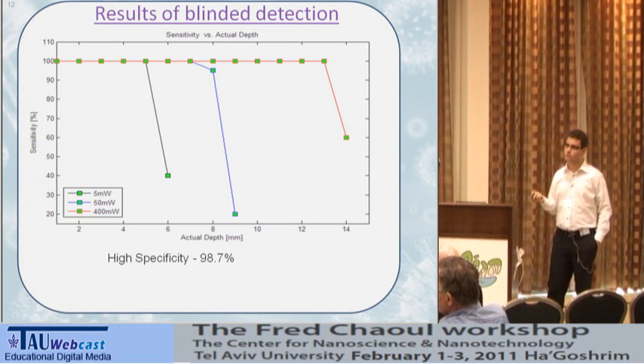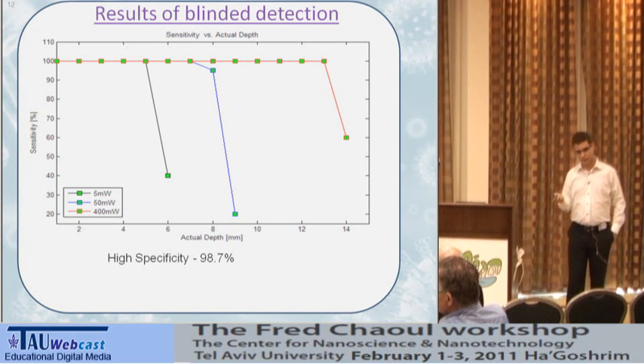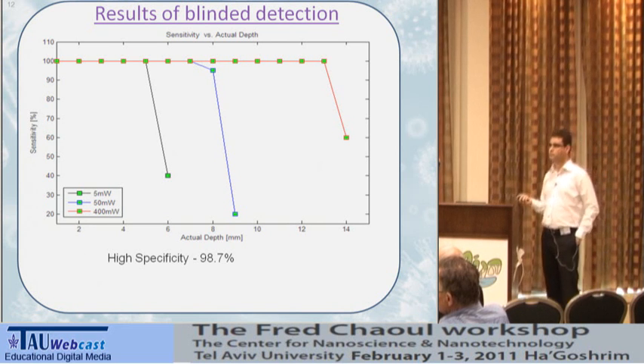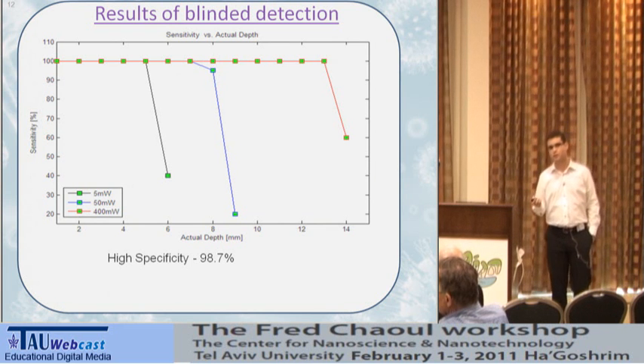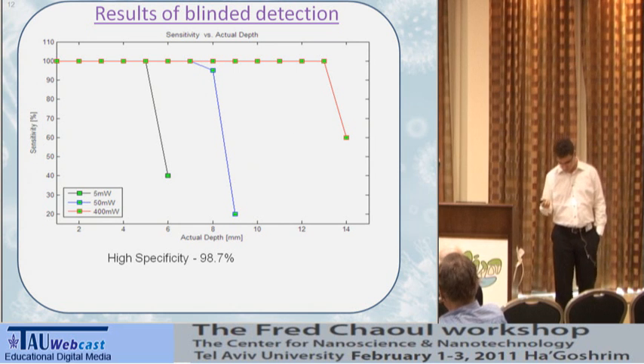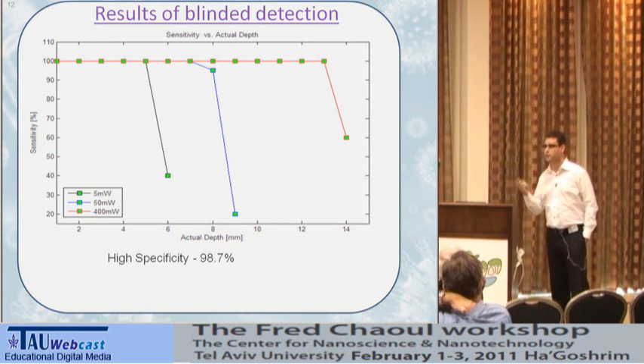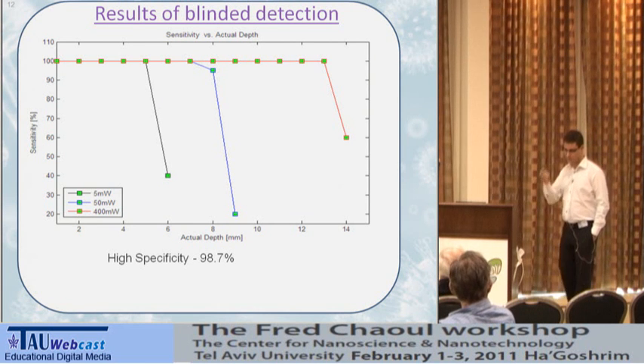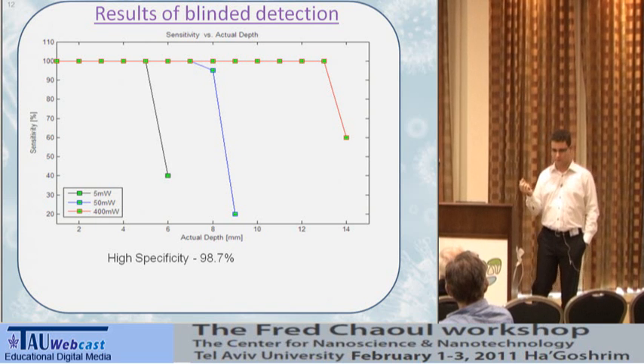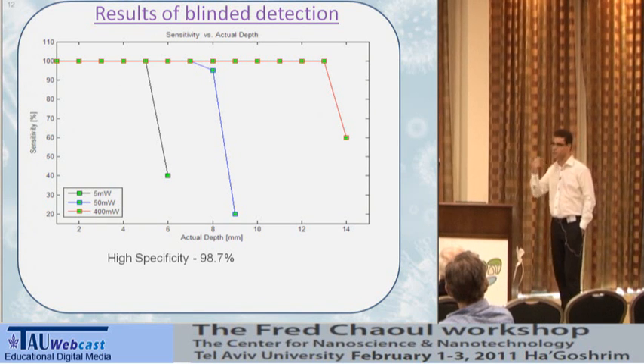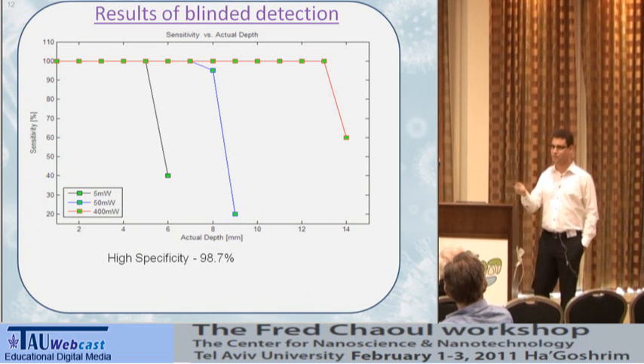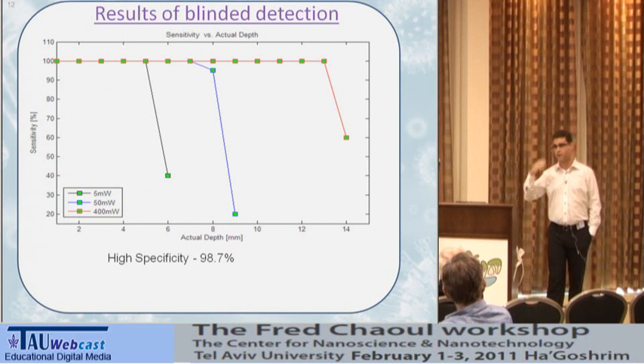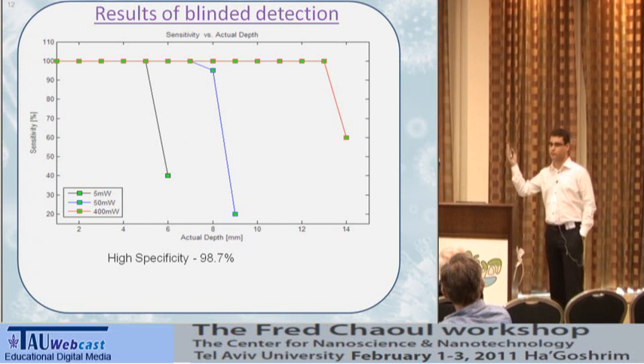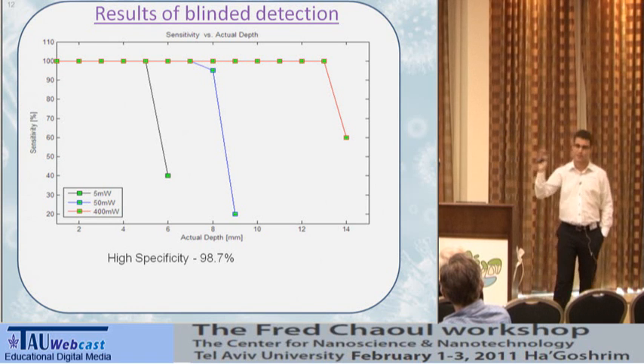So I guess you could also have a non-specific binding of your nanoparticles, right? So that could first introduce some sort of false signal, right? And the other is that you can start worrying about the effect of heating in the non-specific binding. These particles, basically what we used, are called Feridex. This is the commercial name. And they have what the clinician call clearance. It's the amount of time that takes 99 point something percent of these particles to evacuate from the body. So after 24 hours, they have clearance of 24 hours. After 24 hours, every particle will be evacuated from the body, whether it's attached to a tumor or not.